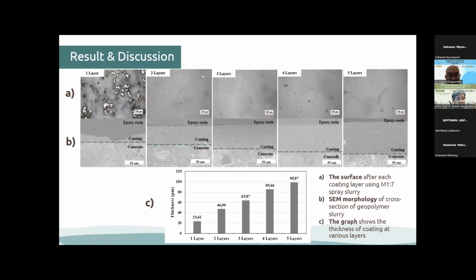Could you give the reason why there was a crack in the first layer? In the first layer, right? Yes, for one layer. For the first coating, the amount of coating sprayed on the surface was not enough for one layer, and the coating was insufficient to cover the whole surface.